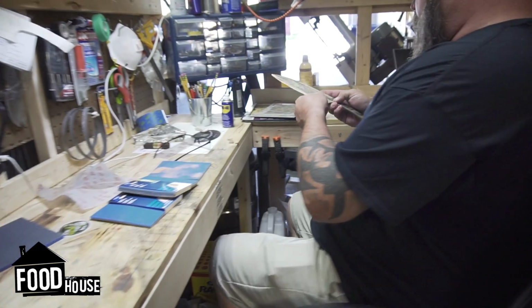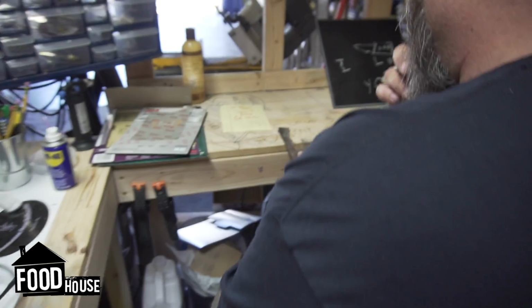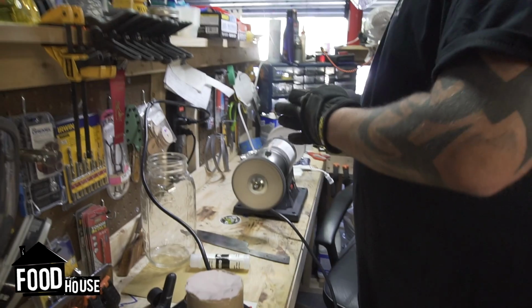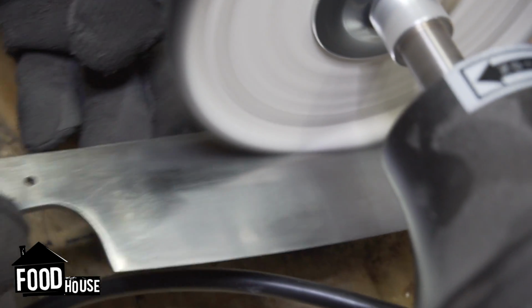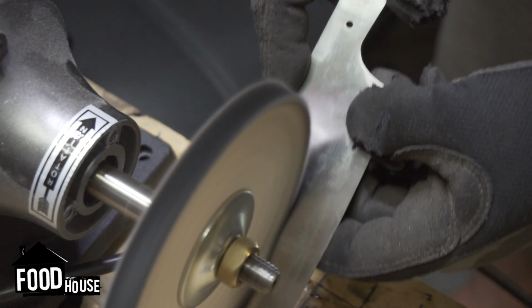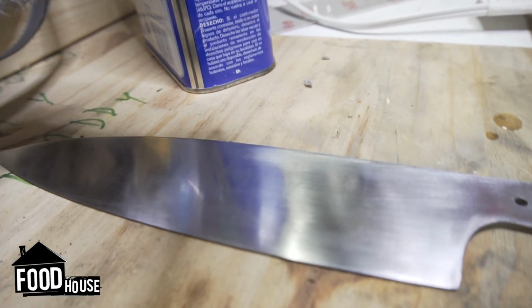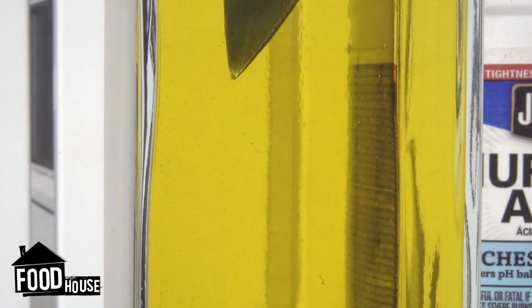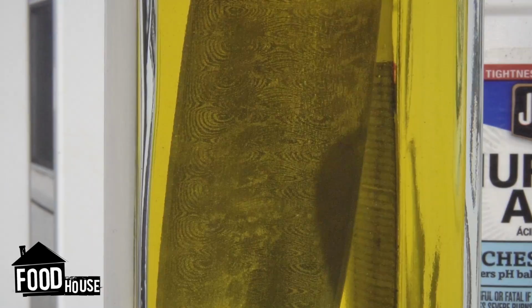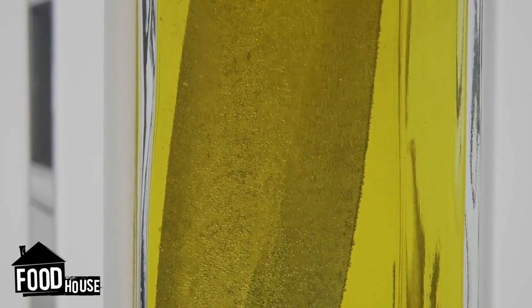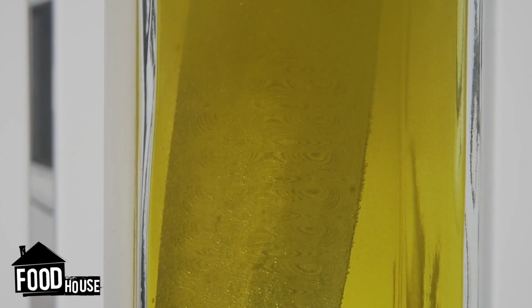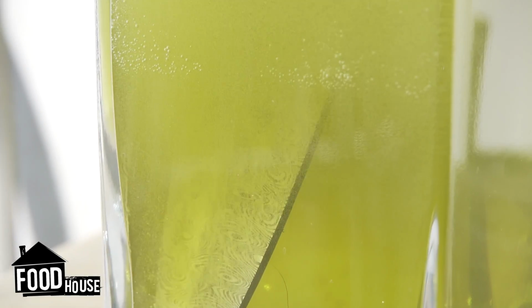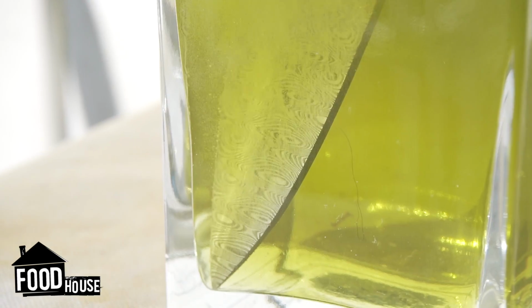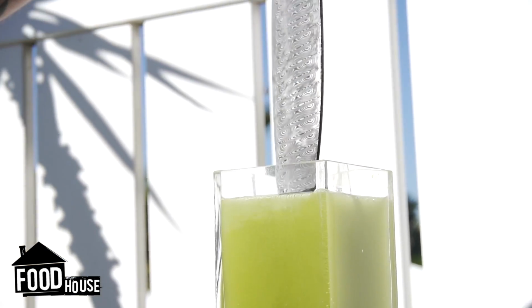After it comes out of the heat treat, it's extremely hard and brittle. The tempering process controls it back to a certain hardness that you're trying to achieve. And my chef knives are normally about 60 on the Rockwell scale, which is how you gauge how hard steel is. Then after that, we throw it in muriatic acid for half an hour. It brings out the pattern in the Damascus steel. Damascus steel is comprised of 2 different stainless steels. So when we put it in the muriatic acid, it actually attacks one of the stainless steels and not the other. And that's what brings the pattern of the steel out.